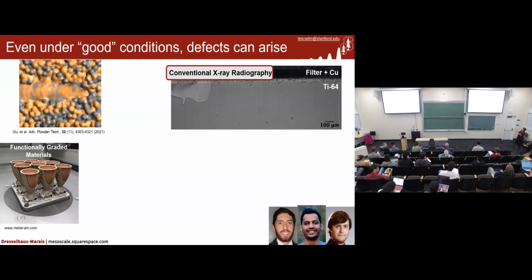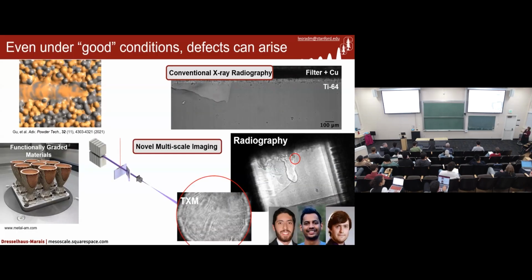So conventional X-ray radiography would look something like this, where we now started to be able to trace this by demonstrating how effectively you're seeing, it looks like smoke here is kind of going over this. The dark region is actually the alloyed material that we're now bringing in at these high velocity conditions. And you can actually now see that the fact that it's darker at the top is now bringing in the copper from the top layer. So we can now start to track these types of mixing events.